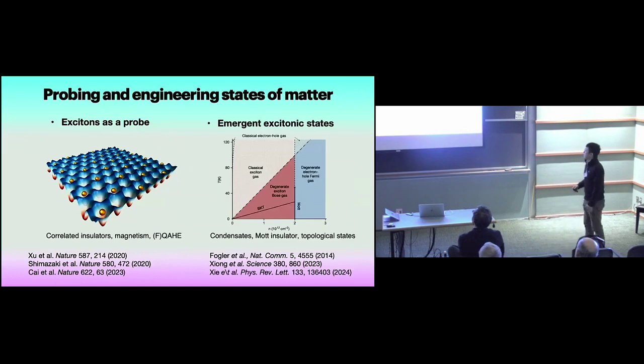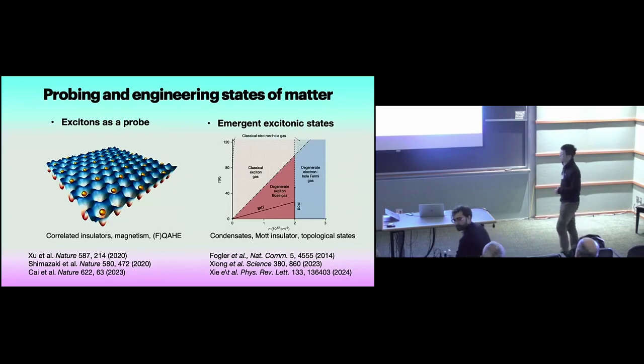On the other hand, the excitons themselves can also have interesting physics, right? If I create a high density of excitons, because of their bosonic nature, it is predicted that they can have this exciton condensate phase at relatively high temperature. In addition, if you put these excitons into a Moiré system, you can create a bosonic Hubbard model. For example, there are predictions of realizing topological states using excitons in such systems.